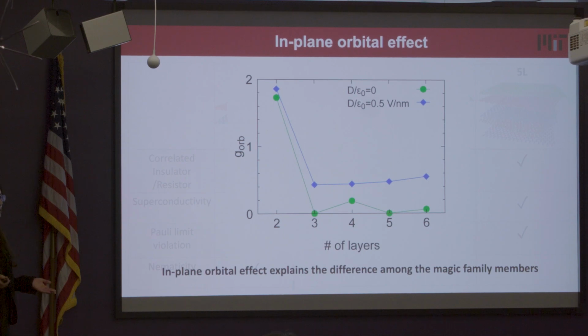Because experimentally, in order to probe that with this in-plane magnetic field, you need to have some mechanism to couple to whatever symmetry is in the system. But if that coupling is done through the in-plane orbital effect, and you don't have that coupling present in the system, you can't really probe it. So that's the whole point. It's not like some system has nematicity and the others don't.